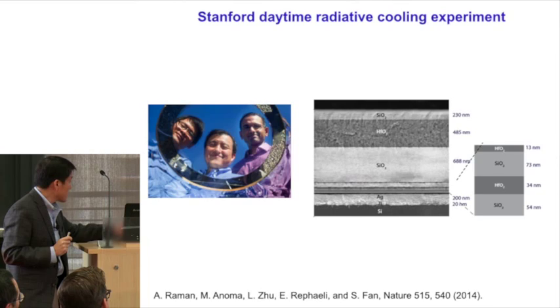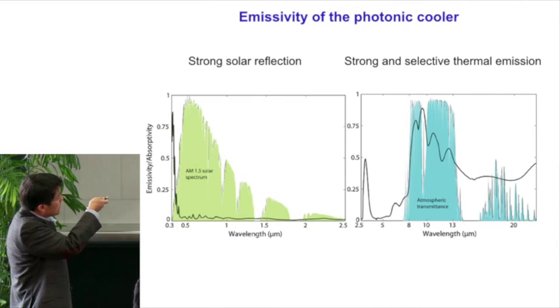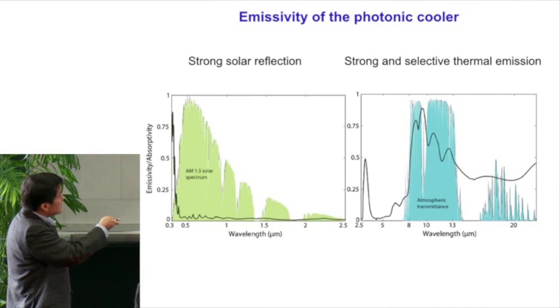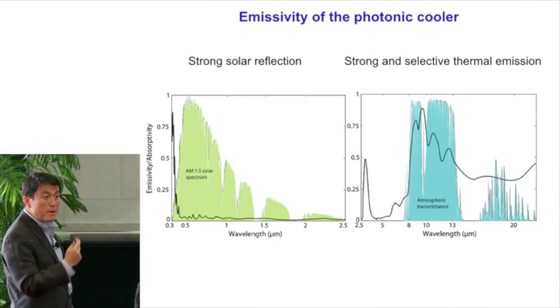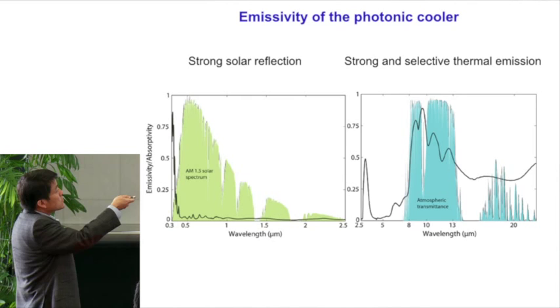And shown here is the solar reflection spectrum. You can see that it has very little emissivity over the entire solar spectrum, except somewhere in the UV. So it actually is a very good mirror, as you see in the picture that I just showed you, yet it emits very strongly in the 8 to 13 micron window.